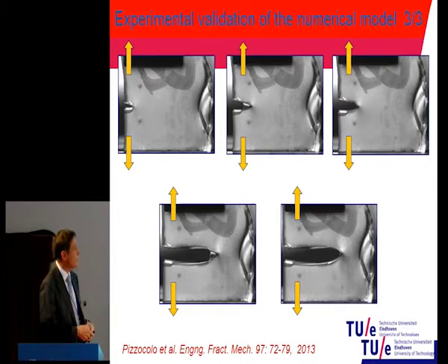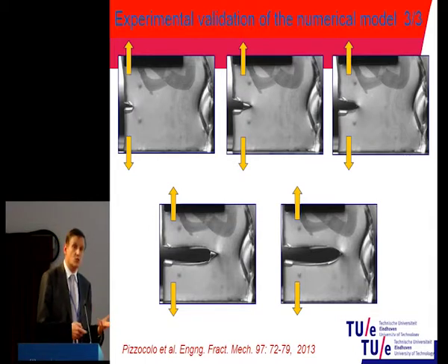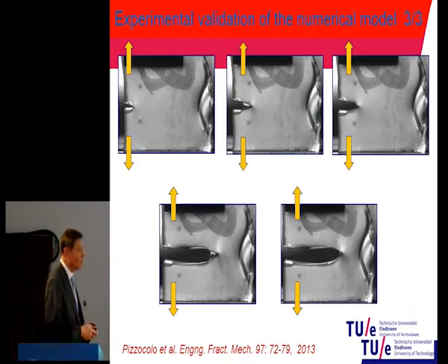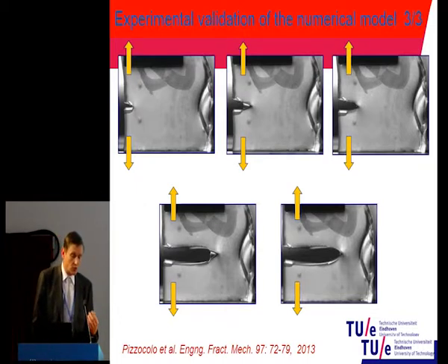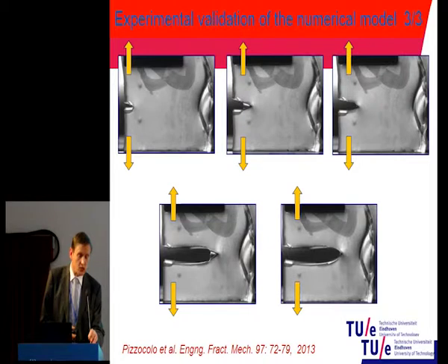propagates in a stepwise fashion. It propagates in a stepwise fashion as soon as you include fluids. You don't need swelling, but you do need the fluid, and you find that it goes in a stepwise fashion, and you see sudden changes in flow, demonstrating that the stepwise propagation is due to the presence of the fluid.